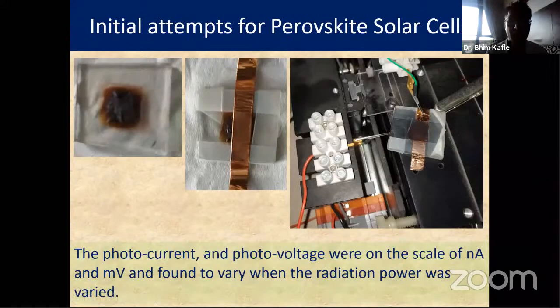And then we tried our best to form a solar cell, putting this GO on the perovskite layer that I mentioned here. This one is copper tape as an electrical contact, because we did not have vacuum deposition. So at first we wanted to try with this, and of course we could not see very nice photocurrent and photovoltaics, but as a signature, when there was no sunlight on top of this, the photocurrent was 0. But once we irradiate the solar radiation, we could see photocurrent on the nanoampere scale, and some millivolt scale voltage.